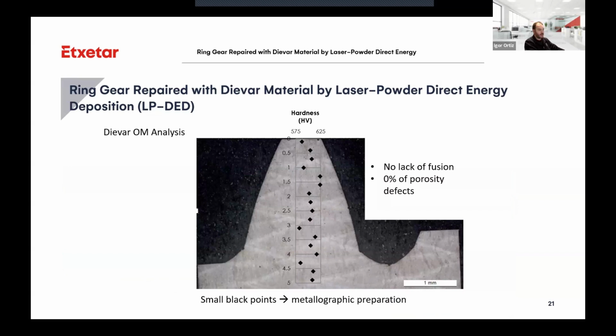And we have taken the measures of a sample of a whole gear tooth manufactured by laser powder direct energy deposition. As you can see, no lack of fusion, zero porosity. The small points represent the hardness in these areas. So we have done different analysis, not just the repair, also building sample tools.